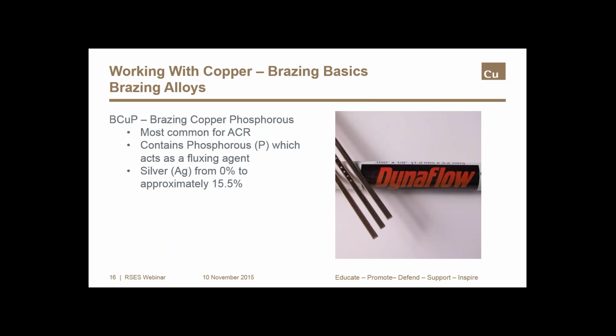The BCuP series is most commonly used for air conditioning and refrigeration installations, and these filler metals have higher melting temperatures than the silver-containing BAg series. There's a BCuP 2 filler that's recommended for close tolerances. There's BCuP 3, 4, and 5 that are recommended for joints where close tolerances cannot be held. Looking at the composition of BCuP filler alloys, there's phosphorus in amounts that vary from about 4 to 7.5%. The phosphorus in this alloy acts as a fluxing agent. So, when joining copper to copper using a BCuP brazing filler, there is no need for a separate fluxing operation.